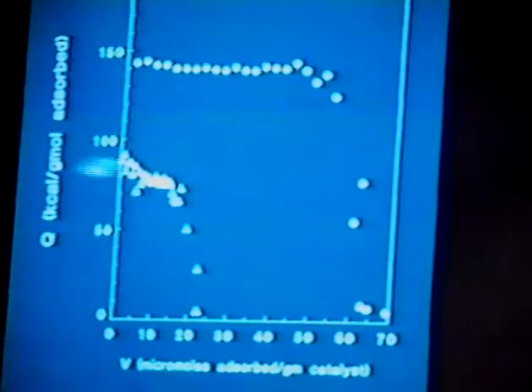In contrast to the oxygen adsorption on a supported rhodium particle, the heat basically drops off from the start and tends to stabilize to some extent for a short period of time and then continues to drop until you completely saturate the surface. In this case, the integrated heat of adsorption by the area under the curve is about 67 kcals per gram, which is substantially higher than the heats of formation of any oxide phase of rhodium. And so we believe that in this case we're actually forming a surface, an adsorbed layer, a true chemisorbed layer on the surface of supported rhodium particles. The important point here is that the heats over the entire range are substantially different between the two metals, and the shape of the curves are substantially different between the two metals.